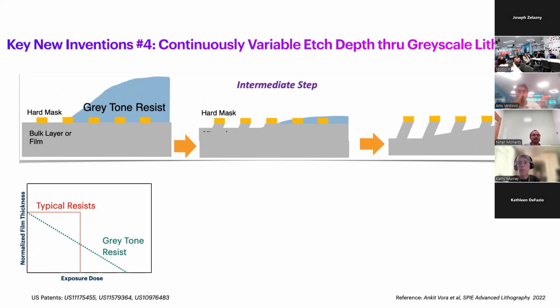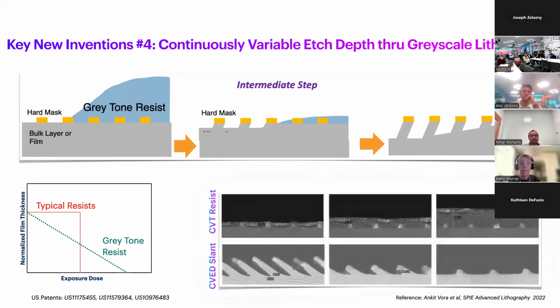We had to go back to the literature from several decades back, to the 1950s and 60s, to identify resist chemistries that were rejected by the semiconductor industry, to identify the grey tone resist chemistries that work for us, that have the desired UV sensitivity, linear dose response, and the target etch selectivity to achieve the variable etch depth. This was a non-trivial multivariate co-optimization that involved novel materials and process research. You can learn more about the detailed chemistries in our previous publication at SPIE Advanced Lithography in 2022.